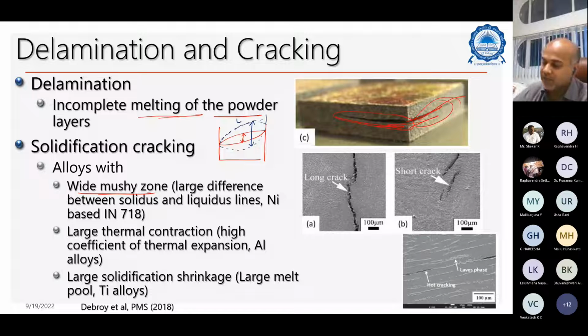Okay. This is the liquidus, this is the solidus, and this region is pretty significant. That is actually called a wide mushy zone material. So large liquidus lines, especially Inconel 718, these kinds of superalloys. In that case, there is a solidification shrinkage. The moment this part gets cooled and some part is still in the liquid state, you tend to see this kind of solidification crack. And again, large thermal contraction, because for aluminum alloys you have a high coefficient of thermal expansion. So there is a large thermal contraction from one layer to other layers that also leads to some kind of solidification crack.